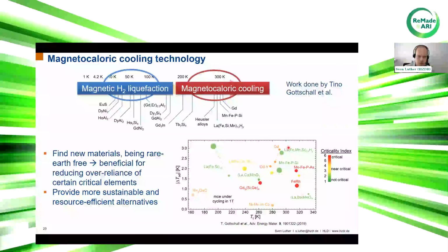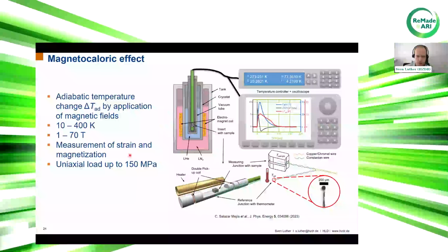So what is actually the magnetocaloric effect? What we measure here is the adiabatic temperature change by application of magnetic fields, because in the pulse fields we are measuring under adiabatic conditions. You can see a diagram of our measurement, where the sample sits inside the cryostat, where we can cover a temperature range from 10 to 400 Kelvin. On the outside, we have our pulse field coil, which is cooled by liquid nitrogen, where we can apply magnetic fields in the range from 1 up to 70 Tesla.